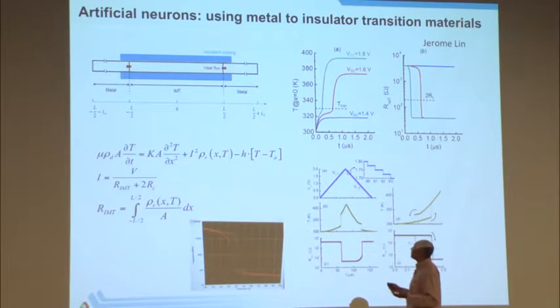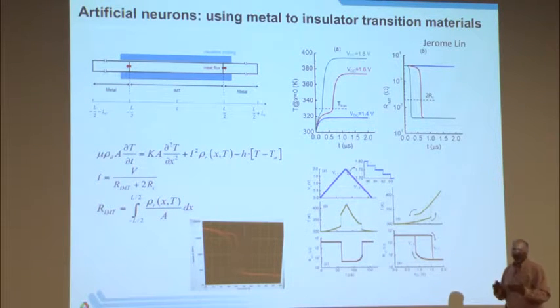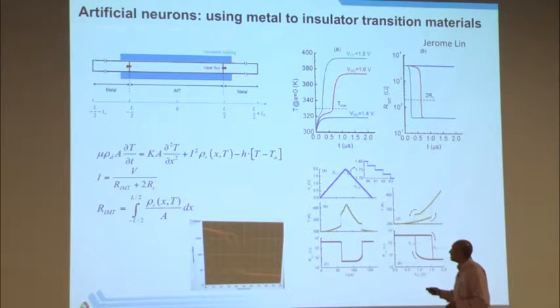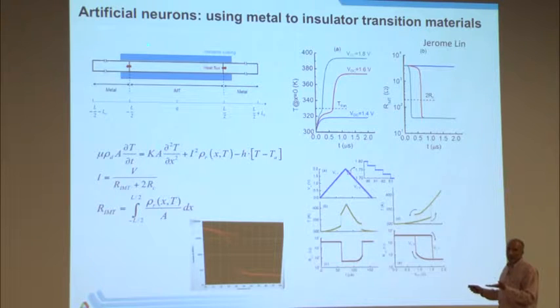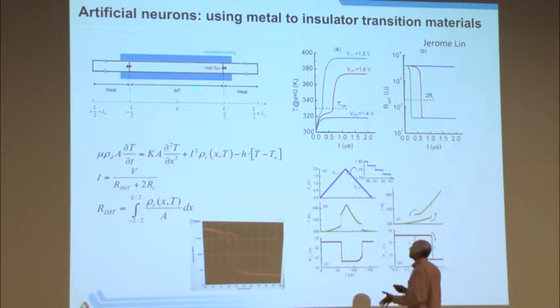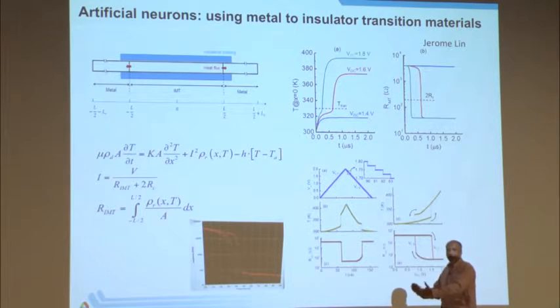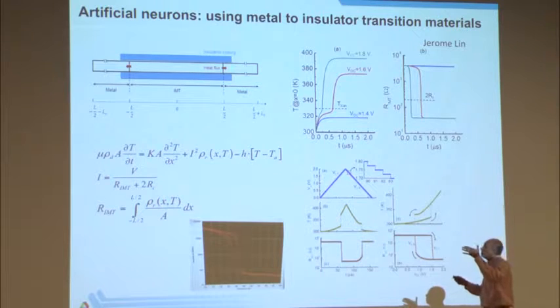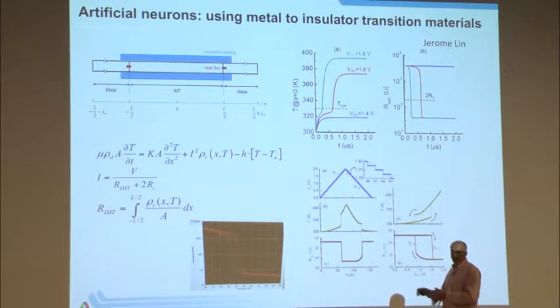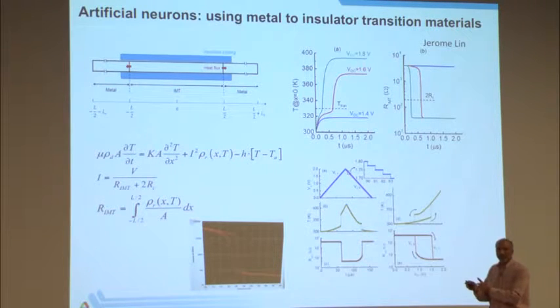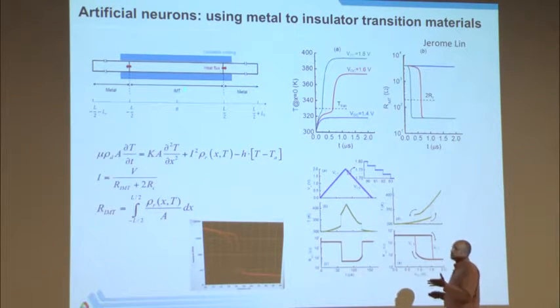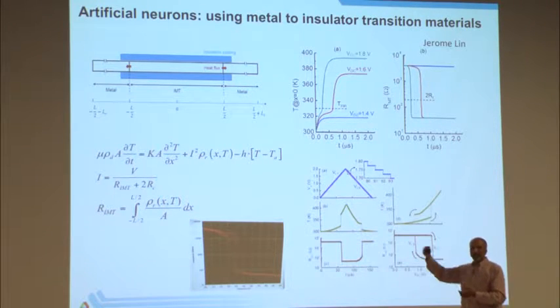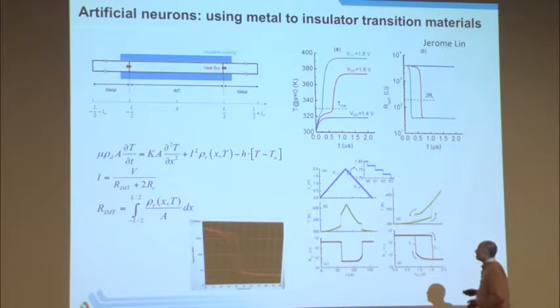So Jerome has been modeling these structures. And this is a very interesting device because it is a combined electrical thermal capacitance type device. When you pass current through this device, it heats up. When it heats up, at one point its resistance drops. When its resistance drops, the current increases. That's the firing of the device. Then when it cools down, its resistance goes up again, and the refractory period is defined by the amount of time it takes to cool down. And the integrate and fire comes from the accumulation of the pulses and the heating of the material. So this can all be modeled in a tedious but conceptually straightforward way.